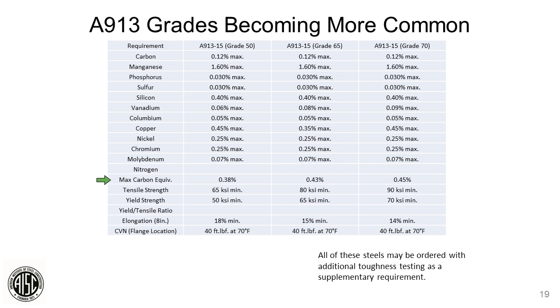But as the tensile strength and yield strength all go up, we're achieving this not through chemistry, but basically through the quenching of the steel, allowing it to self-temper. So you'll have a steel with the weldability of an A992 grade 50, but the properties will be similar to a grade 65. So this is a pretty innovative way of using basically a modified heat treatment process. This is done while we're rolling, and it impacts properties to give us a much more ductile steel, a much more weldable steel, with no more alloy content that affects the weldability of the steel.